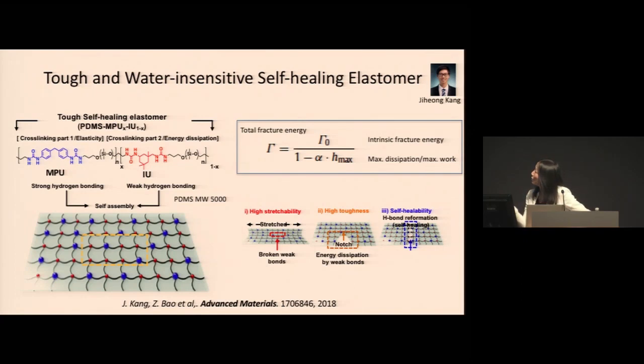So this is a recent generation of material where, instead of a covalent bond combined with the dynamic bonds, we use two types of dynamic bonds, one being a very strong quadruple hydrogen bonding site, and one being a weaker hydrogen bonding site due to the steric hindrance introduced into these moieties. The dynamic bonds still allow energy dissipation when the material is under strain, but with these very strong hydrogen bonds, if there's a defect in the material, these strong bonds will block the crack propagation through this material. Our hypothesis is that this design can potentially allow the material to have a much higher fracture energy.